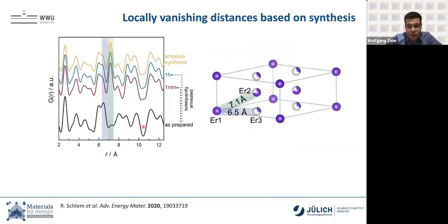Down here, the PDF of the ball mill sample, up here, all the PDFs of the crystallized sample. What we see as a direct difference is that in the as prepared sample, in the ball mill sample, there's one bond distance missing that is prevalent in all of the other ones. And this corresponds directly to this erbium 1, erbium 2 distance. Whereas there's an additional distance here in the ball milled material that is not really there in the crystallized materials. And this is the erbium 1, erbium 3 distance.